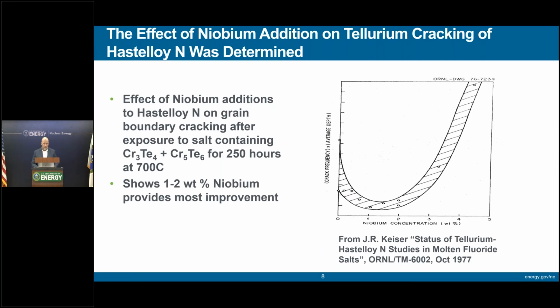The effects of niobium additions on tellurium cracking of Hastelloy N was determined. The effects of niobium additions on grain boundary cracking after exposure to these two chromium tellurium salts for 250 hours at 700 C is presented. It shows 1 to 2% weight niobium provides most improvement.